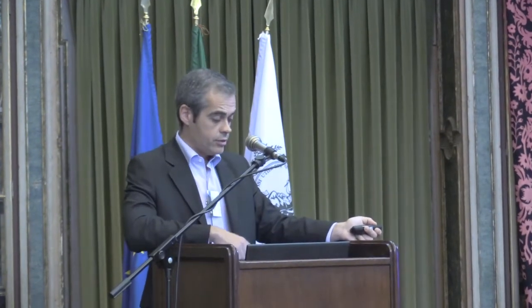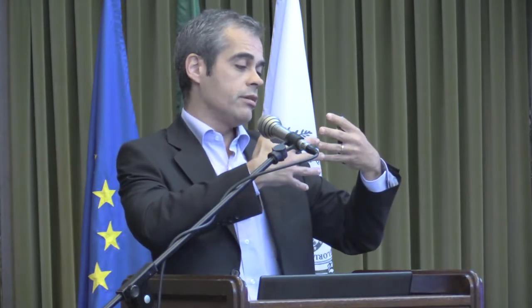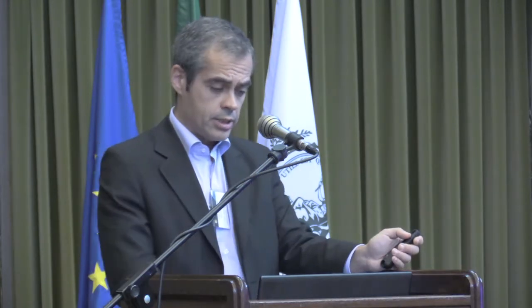Just very briefly, with electrolytes instead of normal dielectrics, you can build up huge capacitance using this kind of structure, basically electrolytic capacitance. You have an electrolyte with ions. You can displace these ions, keeping the charge neutrality in the bulk, but accumulating ions at the interfaces. You have charge separation here. You induce opposite charge in the semiconductor, so you have charge separation in a very narrow space, so a very big capacitance can be built up at these interfaces. This means that with very low voltage you can operate these devices. This is very good if you want to think about printed systems or autonomous systems.